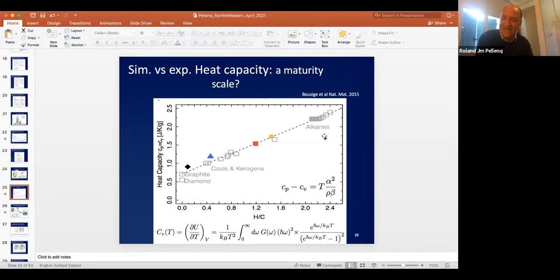Anyway, one way to validate is to take this carbon structure and calculate the heat capacity, for instance, from our simulation and compare to experiment. You see the different samples that we have. These are the colored points. Different colors mean different chemistries. The yellow and red contain more carbon, so they're more like cellulose. The others contain mostly carbons and are closer to what lignin has become. But clearly we are on the experimental line that spans from graphite and diamond up to alkanes. At the end of the day, we calculated the vibrations, so this is really a way to probe whether the chemistry is correct.